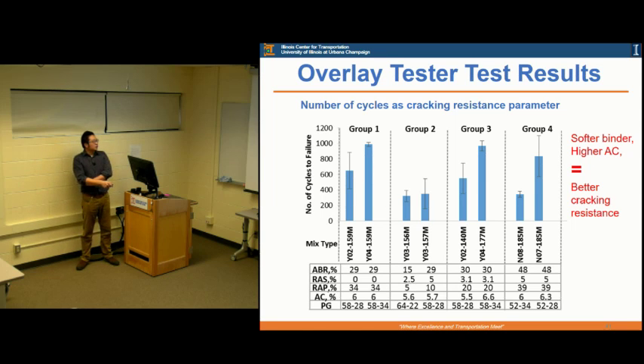And also if you compare these two, one has a little higher AC content, then you end up with much better cracking resistance. So we can see that if you use a little softer binder and also relatively higher asphalt content, your mixes get a better cracking resistance.